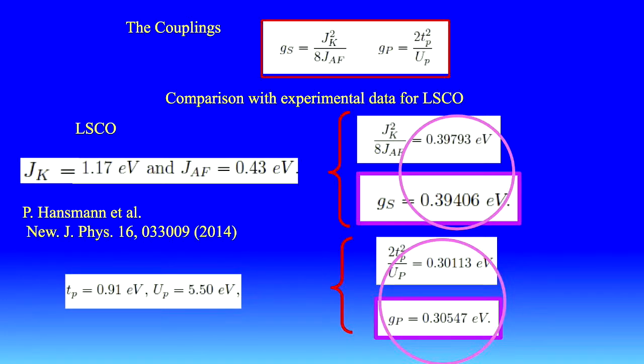And here, we have this. So this is the first indication that we were on the right track. Excuse me? You mean the first one or the second? Okay, the first one comes from the spin fermion model. When we make the transition from the three-band Hubbard model to the spin fermion, we determine the effective couplings of the spin fermion model in terms of the original three-band Hubbard parameters. So these are not really measured. These are calculated when you make the transition from the three-band Hubbard model to the spin fermion.